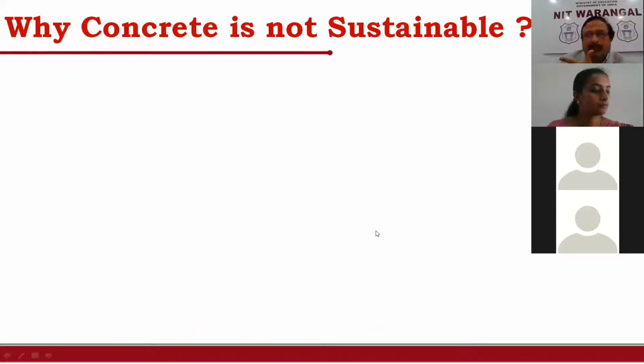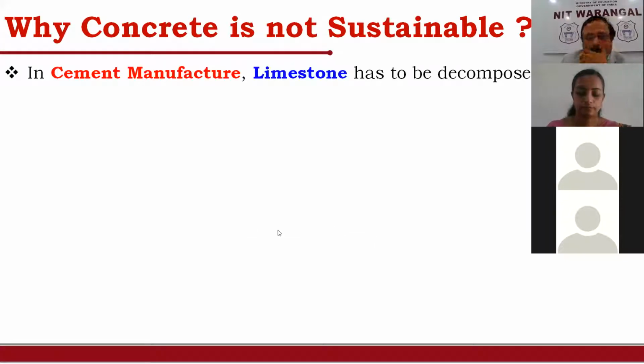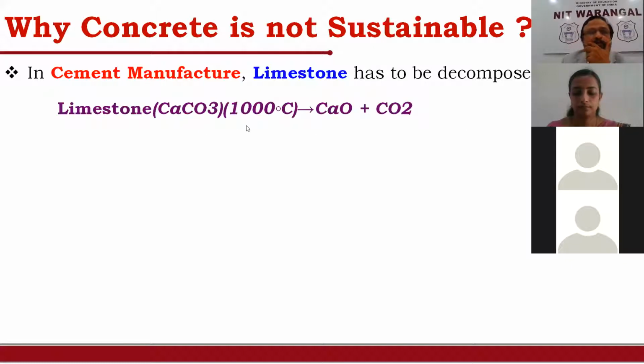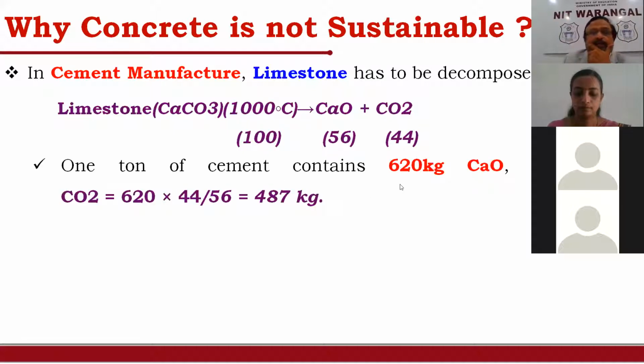So why is concrete not sustainable? The reason is in cement manufacturing, because cement is an important ingredient of concrete. In cement manufacturing, limestone has to be decomposed. This is the equation: calcium carbonate at 1000 degrees centigrade breaks into calcium oxide and carbon dioxide. If 100 units of limestone is burned, you get 56 of calcium oxide and 44 of carbon dioxide. So 1 ton of cement contains 620 kgs of calcium oxide, and hence almost 487 kgs of carbon dioxide is emitted.